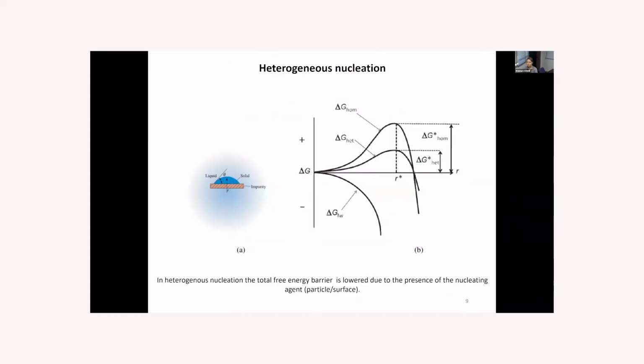So heterogeneous nucleation is a modified version of the homogeneous nucleation when a third party, such as a surface or particle or any other dust, is inducing the nucleation by lowering the total free energy barrier, because the surface energy of the interaction between the surface and the ice nuclei is lowering the total free energy. And hence the nucleation is facilitated.